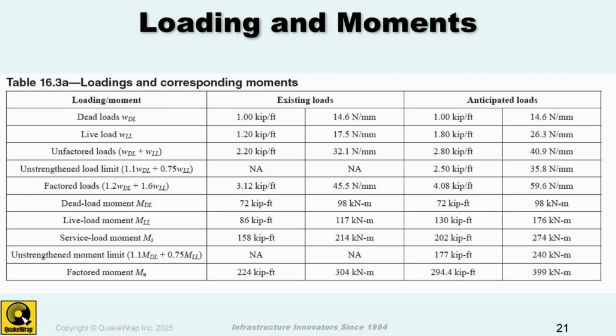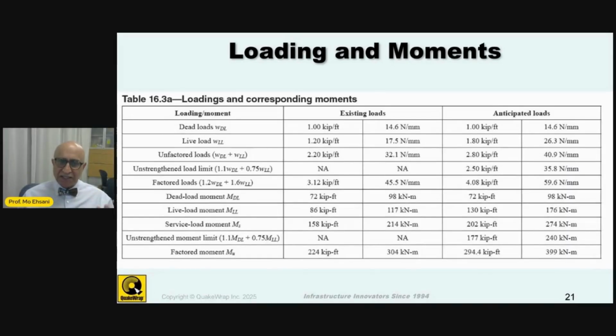One of the things about ACI 440, even though there are a lot of laboratory tests, is that in the studies that have been done, people have shown that you can get the strength of these beams to go 3 times as much as the unretrofitted one. But the code has taken a conservative approach, and so you're allowed to increase the flexural capacity by only roughly in the order of 30 to 40% with some of these checks that you see in here.